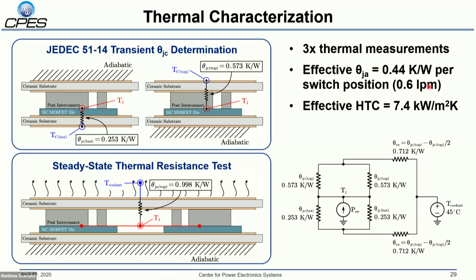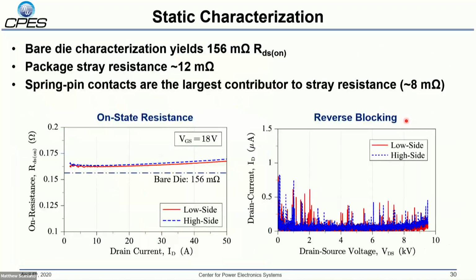The cooler was designed for a little bit faster than that, but I'm walking it up slowly because I want to see what happens. So we're starting out slow at 0.6 LPM, and as we go on, hopefully we can get this up to 2 LPM. But at that 0.6 liter per minute flow rate, we're at about 7.4 kilowatt per meter squared Kelvin effective HTC.